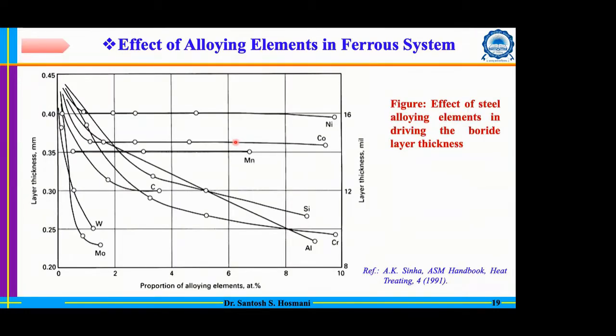Now, another important aspect is the composition of the ferrous alloy. Actually, this is a very complicated concept of behavior, especially in the case of boronizing, which is actually the least understood. During boronizing of these ferrous alloys, various elements have different responses. For example, elements like chromium, aluminum, silicon restrict the boride growth. However, elements like cobalt, nickel, manganese don't have much effect on restricting the boride growth.